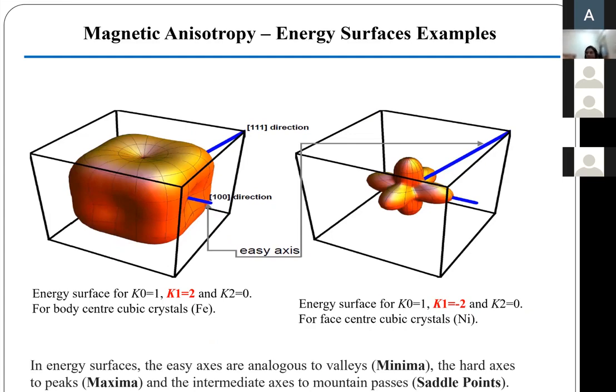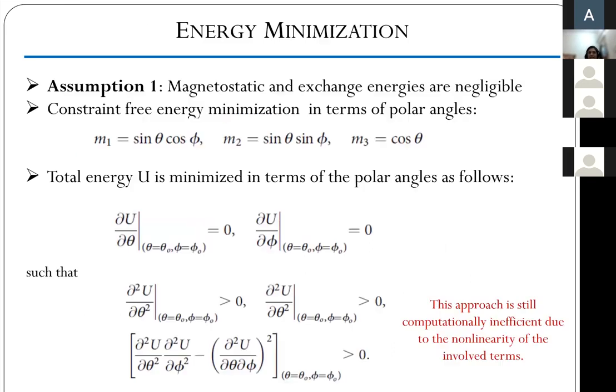But once we apply a magnetic field, or when we apply a stress, several of the energies that I talked about previously become non-zero and relevant. Then it becomes minimization of the total energy, right? So the interplay between all of these terms, and the resulting minima from that, is how we calculate the magnetic moments, the magnetic orientations within each domain, and then the total magnetization, which is the sum over all the domains. So the response of all the domains.